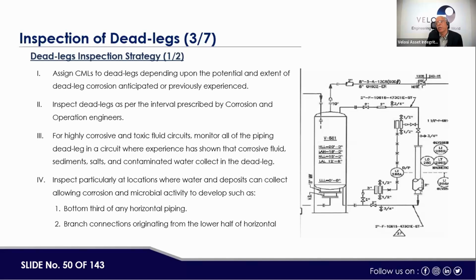So we have to keep in mind, if I go through my presentation points: assign CML to dead legs depending upon the potential and extent of the dead leg corrosion anticipated or previously experienced. Inspect dead legs as per the interval prescribed by corrosion and operation engineers. For highly corrosive and toxic fluid circuits, monitor all the piping dead legs in a circuit where experience has shown that corrosive fluid, sediments, salts, and contaminated water collect in the dead leg. Then inspect particularly at locations where water and deposit can collect, allowing corrosion and microbiological activity, like biological corrosion or SRB corrosion, which can be a faster damage mechanism.